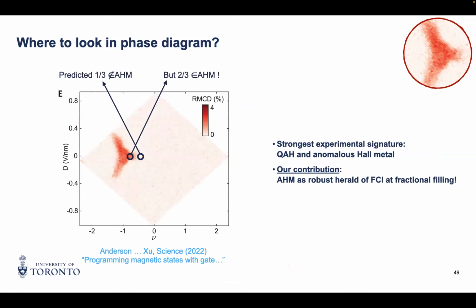Right. But okay, so we have predictive power, but we were wrong though. So I think fraction 1/3. If you look at the experiments, there's no ferromagnetism. So we were probably using an interaction that was too big. But if you look at the density range in which ferromagnetism appears, 2/3 is in there. So you could still ask the question, well, it's a fractional filling. So there's a competition between the charge density wave and the fractional quantum Hall analog. And for that, you need to do the experiment. And the experiment showed that it was indeed the fractional quantum Hall analog that was lower in energy and stabilized.